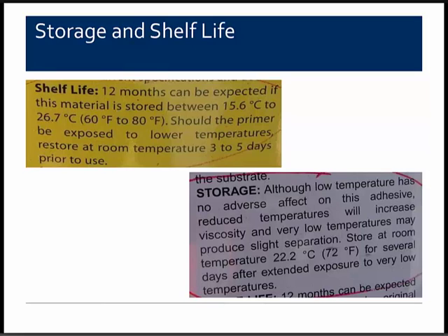But should it be stored at a low temperature, they want you to bring it up to 72 degrees for several days after exposure. The other prior one says 3 to 5 days. So what's important here is that each manufacturer is different, so you must read the labels and verify dates of the products are clearly visible.